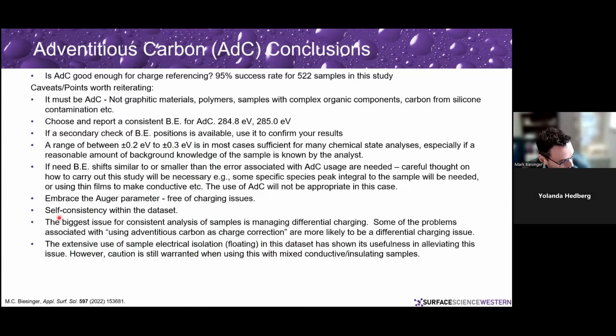The big result was, well, how good does the adventitious carbon charge referencing technique work? And how did you judge that? Well, we judged that by, did we get results that were consistent? Did they make sense? Were they backed up by other things? Did it make sense with all the other peaks, and were you able to say, okay, I could pull out relatively easily a good chemistry for this sample. And so for the 522 samples from this study, we found that we had about a 95% success rate using adventitious carbon as a charge reference.